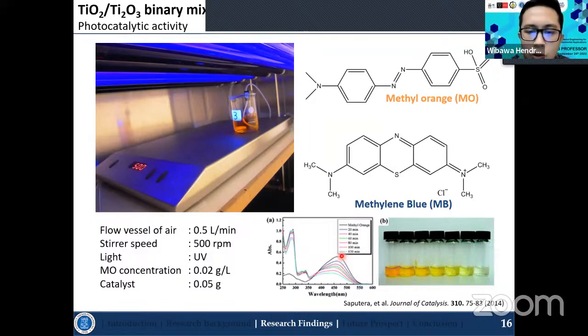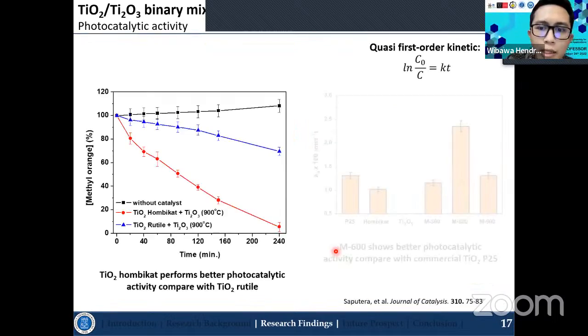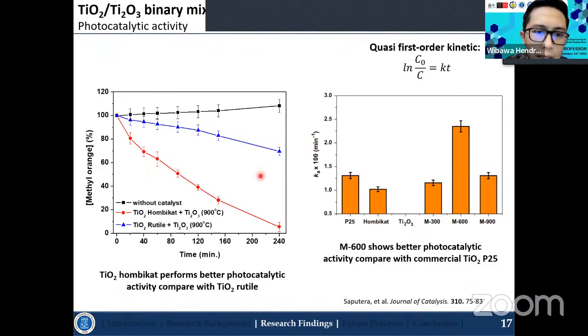It's also in line with the concentrations detected from the UV-vis absorption spectroscopy. And based on the photocatalytic activity, it can be seen that the TiO2 anatase mixed with the Ti2O3 is more active compared with the TiO2 rutile and also without the catalyst, which we call photolysis. For the photolysis process, there is no degradation of the methyl orange, and it is confirmed in the right-hand side table, where the M600, the yellowish TiO2, is the most active catalyst compared with other calcination temperatures and also the control materials like the TiO2 P25, which is already commercially available at the moment, and TiO2 anatase, as well as the Ti2O3.